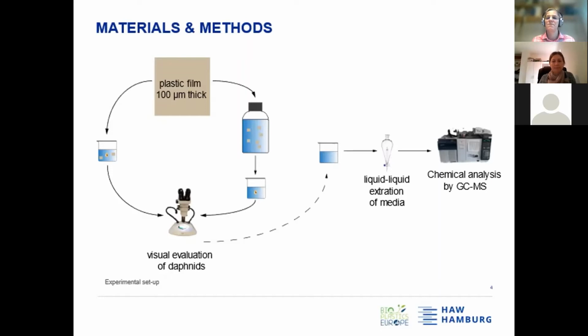And we also tested the leaching of pollutants from the bioplastic materials, and therefore we put the thin plastic sheets into a bottle with medium, and they were shaken for 14 days in the dark. Afterwards only the medium without the plastic sheet was tested in the acute and chronic tests.